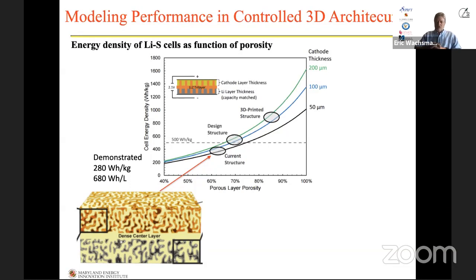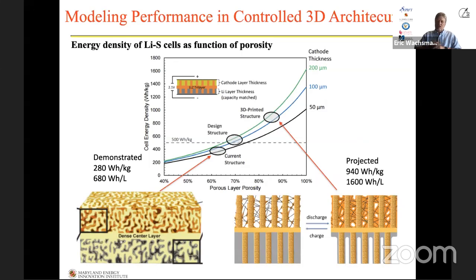But the thing is that now we have the ability to look at how we tailor the porosity in these structures and how that affects the overall cell energy density. And what we're seeing is that, if we make this all 3D structure type battery, we can potentially get about 940 watt hours per kilogram, about 3-4 times that of conventional batteries that are on the market today.